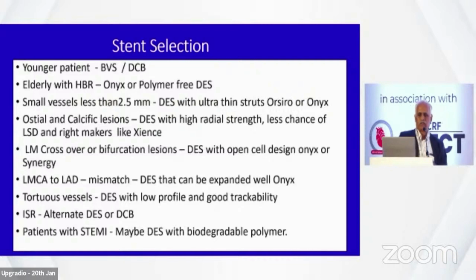If you have a small vessel with less than 2.5 millimeters, you use the ultra thin struts like Orsiro or Onyx. If you've got ostial calcific lesions, use a stent with good visibility and radial strength and less chance of longitudinal stent deformation. Probably Xience will do well. If you're doing a crossover stent, especially across a big branch like circumflex or a large diagonal, you should have access to the branch. So choose one with open cells like Onyx or Synergy.